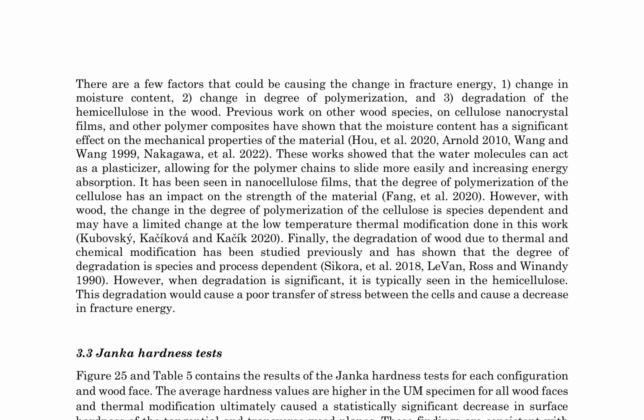Thermal and chemical modification can also lead to degradation, primarily affecting the hemicellulose component, which compromises stress transfer between cells, resulting in decreased fracture energy. Janka hardness tests indicate that average hardness values are higher in unmodified specimens for all wood faces. Thermal modification (TM) caused a statistically significant decrease in surface hardness of the tangential and transverse wood planes.